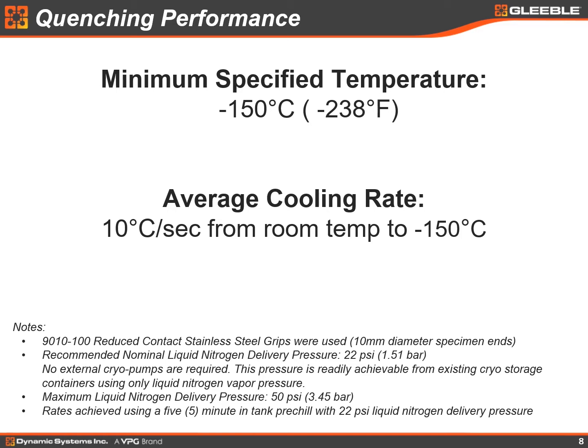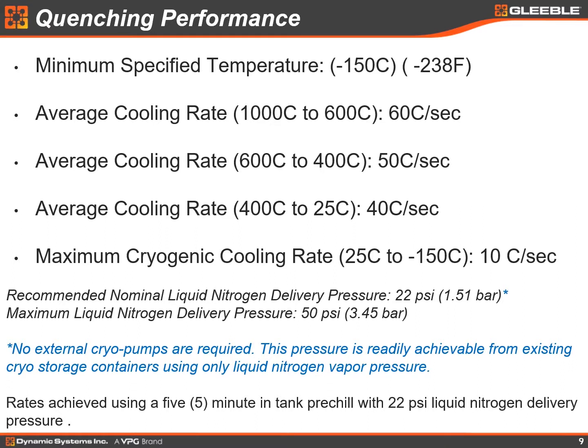So for temperatures above the boiling point of water, water is actually probably a faster quenchant, but obviously you can only get down to 100 C at a very fast rate using water as a quenchant. Of course, the cooling rate does vary with the temperature of the sample, and this table here simply shows how that cooling rate changes. At higher temperatures, between 1000 C and 600 C, we get about 60 degrees per second in the ISOQ setup, and that falls off to that 10 C per second I talked about before as we reach those room temperature down to cryogenic temperature ranges.